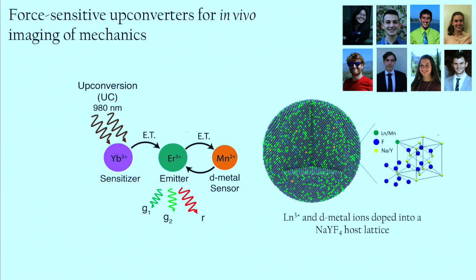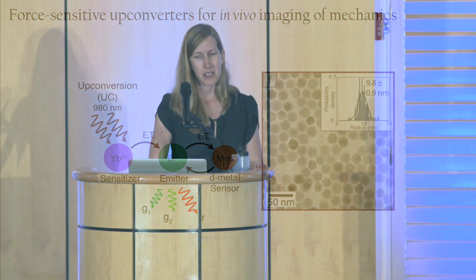And the idea is that you can turn on and off the energy transfer between the erbium and the manganese. And all of these are then doped into a host lattice, usually a sodium yttrium fluoride host lattice, although if you go to our poster, you can see some new host materials that we're working with at this point. So we dope all of these ions into a ceramic host lattice that's biocompatible, and then we make nanoparticles that are sub-20 nanometers in size.